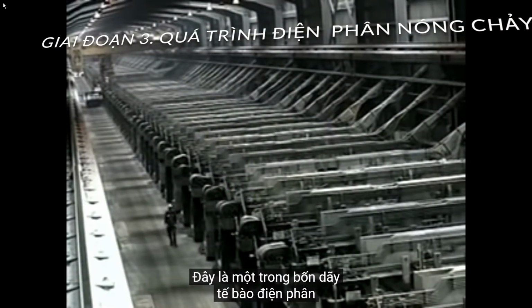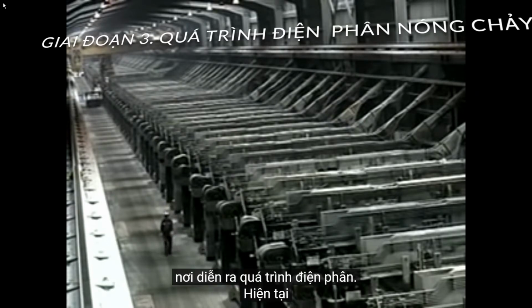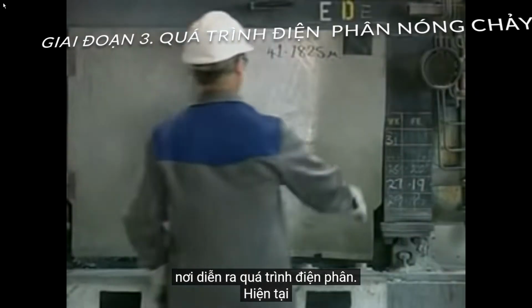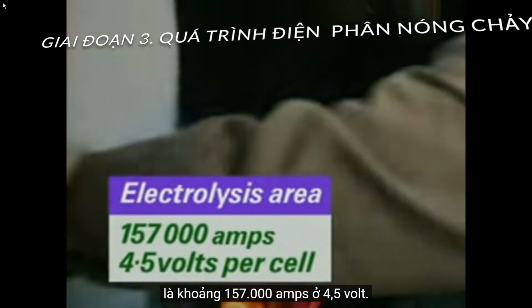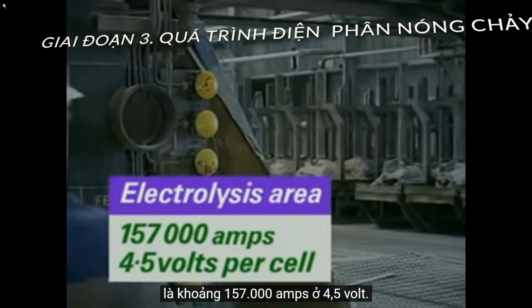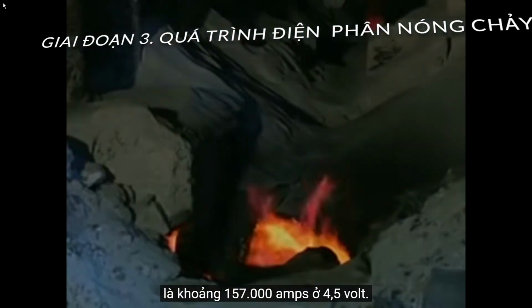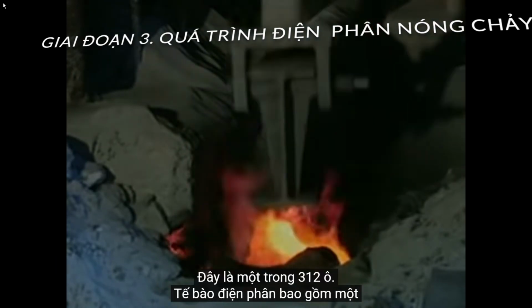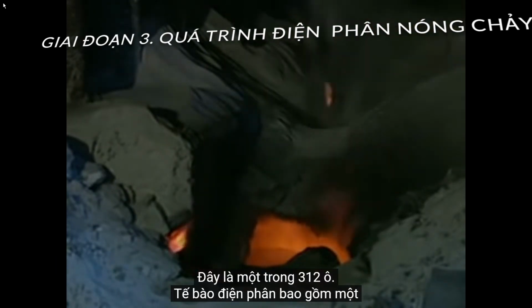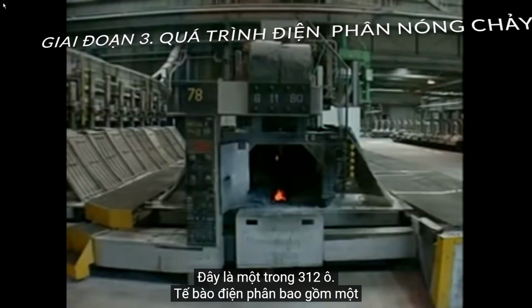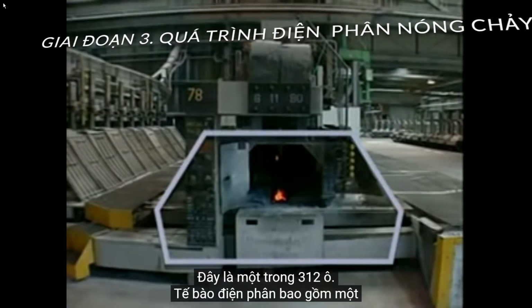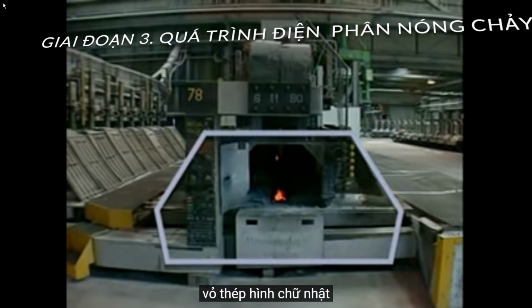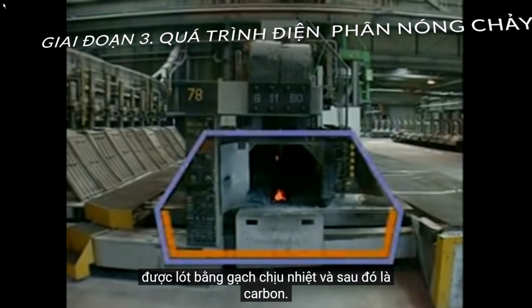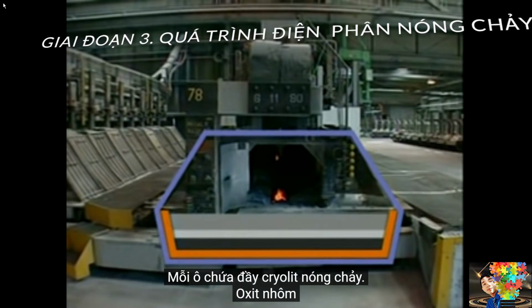This is one of the 4 rows of electrolysis cells where the electrolysis takes place. The current is about 157,000 amps at 4.5 volts. This is one of the 312 cells. The electrolysis cell consists of a rectangular steel shell lined with heat-resistant brick and then carbon. Each cell is filled with molten cryolite.